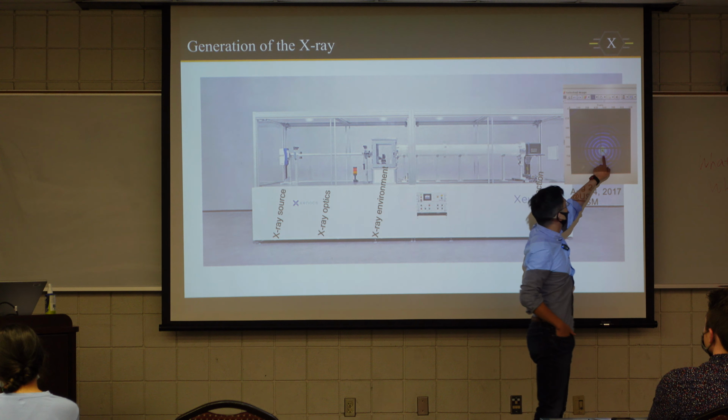Yes! Both of you are right. So scattering angle, or 4 pi sine theta divided by lambda. So 4 pi and lambda are defined, but you only need to measure the angle. So how do we measure the angle using this instrument? It's coming from this paragraph. So it's a simple triangle relation.